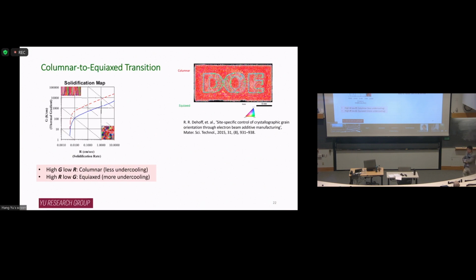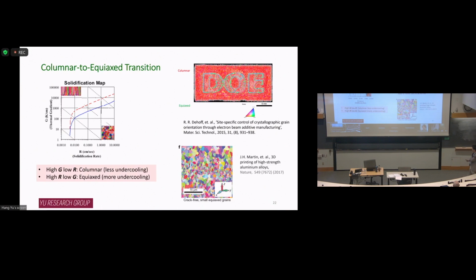Another way to do it, demonstrated by folks at UCLA, UCSB, and HRL, is to add nanoparticles to your feedstock. Those nanoparticles have a high melting temperature and can serve as heterogeneous nucleation sites inside the molten pool. So you still have heterogeneous nucleation, but it's inside the molten pool, so you can get an equiaxed grain structure as well. Okay? So that's what people have done in the field of fusion-based additive manufacturing to control the microstructure.